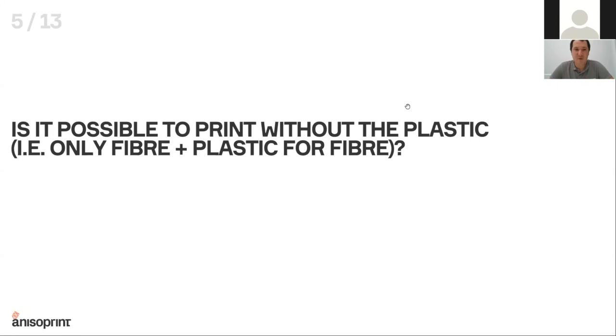Is it possible to print without the plastic? Only fiber, and plastic for fiber. In Aura, if you are doing slicing in Aura, it's not possible to print without plastic. Aura will always have a plastic shell, at least one external plastic shell. But we have a separate tool where you can completely freely design every trajectory for the fiber and for the plastic, and you can print even without plastic.